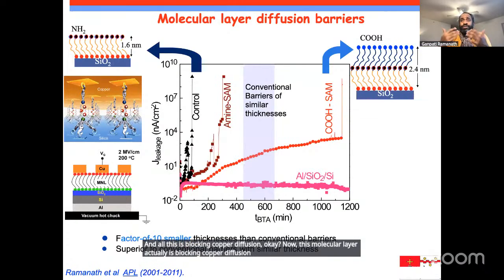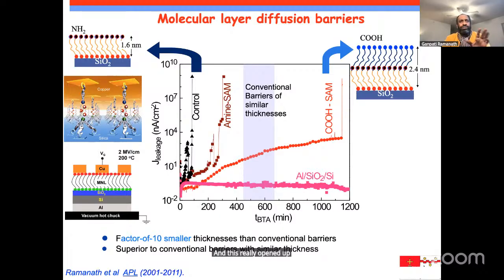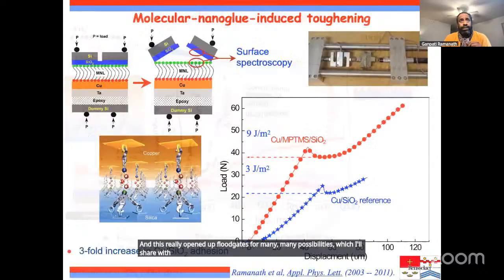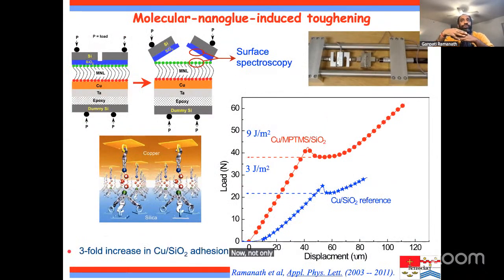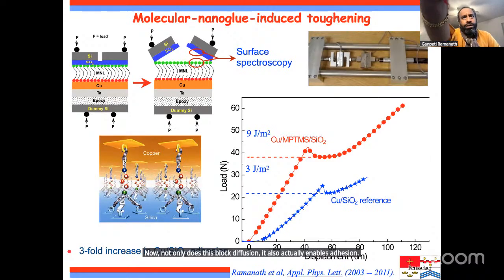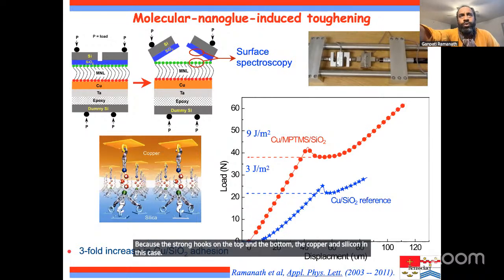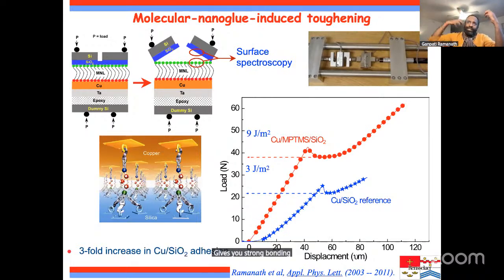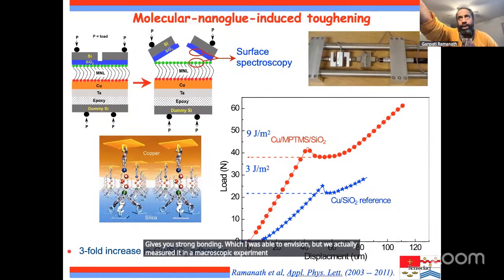And we had to do this about 50, 70 times for me to really believe it, even though I had hypothesized it originally. And this really opened up floodgates for many, many possibilities, which I'll share with you in the next few minutes. Now, not only does this block diffusion, it also actually enables adhesion, because the strong hooks on the top and the bottom with the copper and silica in this case gives you strong bonding, which I was able to envision, but we actually measured it in a macroscopic experiment with 4-point bending that is shown on the